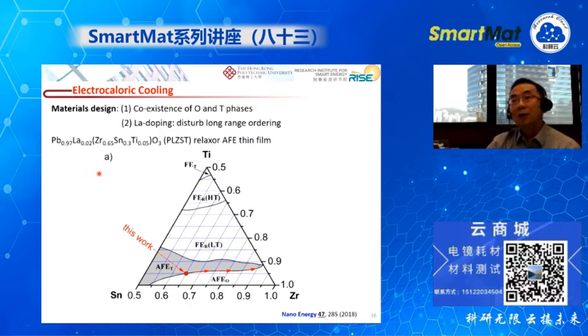Let's talk about our material selection first. Similar to the parallel plate capacitor case, here we also choose a material with the coexistence of different phases. This is the lead zirconate material, with the B site replaced by tin and titanium. These three elements form a phase diagram here, and we choose the material composition near the antiferroelectric phase boundary, where one side has a tetragonal phase and the other has an orthorhombic phase. Then we also add some doping, similar to the previous work. We add some lanthanum doping to disturb the so-called long-range ordering, to introduce some relaxor behavior into the thin film.